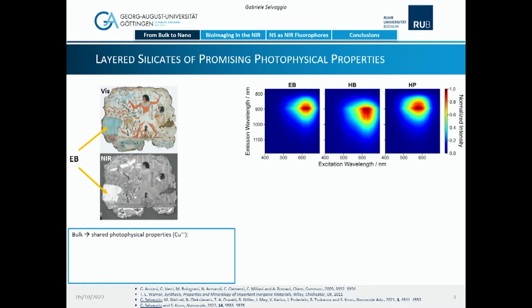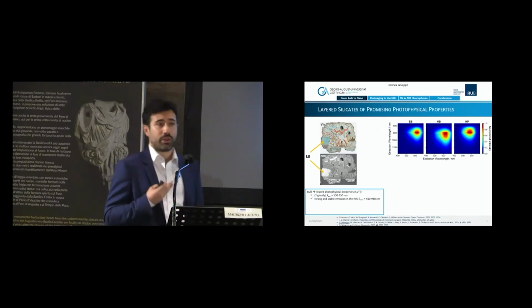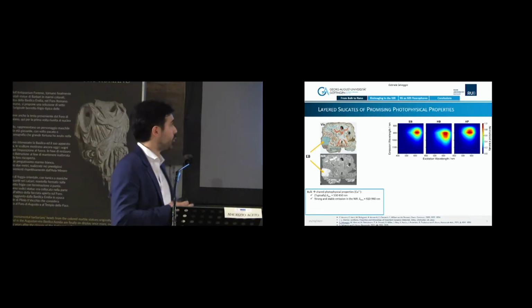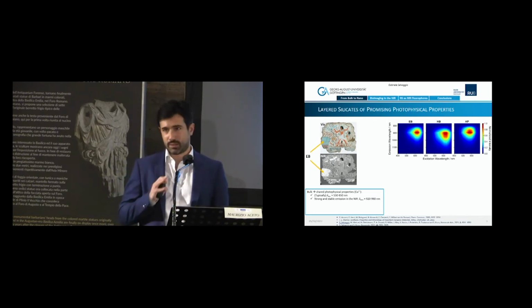These photophysical properties can be nicely described in so-called 2D excitation emission spectra, which show Egyptian blue, Han blue, and Han purple in this case. And you can see here that typically you excite these materials in a broad range in the visible, and above all, that you can get a clear near-infrared emission, which has center wavelengths between 920 and 960 nanometers, roughly.